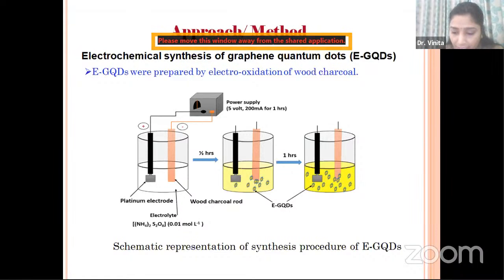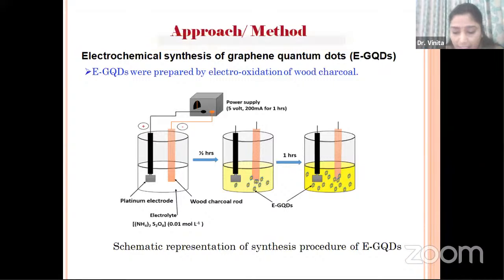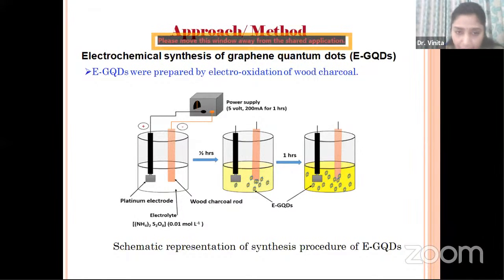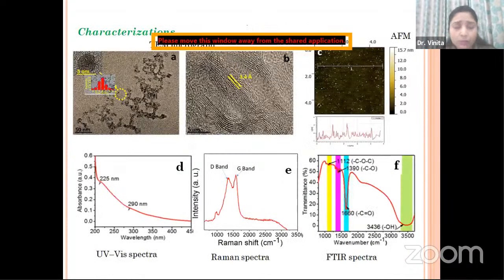ammonium persulfate, which produces sulfate ion radicals that work as a strong oxidizing agent. These sulfate ion radicals may function as sharp electrochemical scissors to cut the graphene sheets into very small intact sp2 structures, namely quantum dots, by oxidizing the carbon-carbon bonds. So these are the characterizations of the quantum dots.